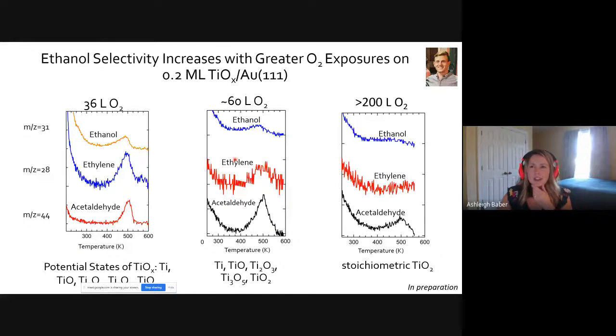But we tried this and we used a much smaller coverage of titania. So looking at about 0.2 monolayers of titania, first dosing very small amounts of oxygen. And we can see that we have some ethanol. We have a lot of ethylene that's desorbing from the surface. That would be the reduced product, and a good amount of acetaldehyde as well. And from that paper, you would expect many different oxidation states to be present on the surface with titania. If we add more oxygen, then we can start to see that this is a bit noisy, the ethylene peak, but you can see a decrease in intensity and we have an increase in the acetaldehyde peak. And when we make our way to stoichiometric titania, we were barely seeing any ethylene at all and seeing only acetaldehyde. And it looks like less overall, but we were able to see that selectivity.